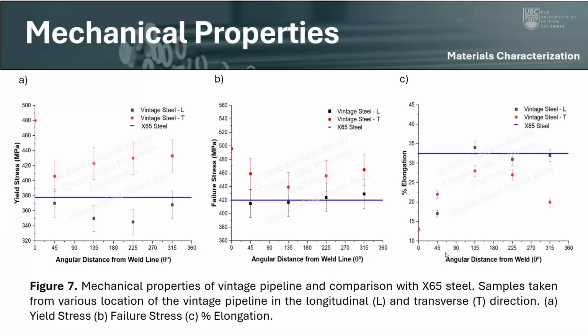So generally, we would want to have similar properties between both the longitudinal and transverse dog bones, but we can see from the yield strength that those are deviating in opposite directions. Also, the values are also differentiated along the circumference of the pipe. I specifically want to comment on the failure stress and percentage elongation.